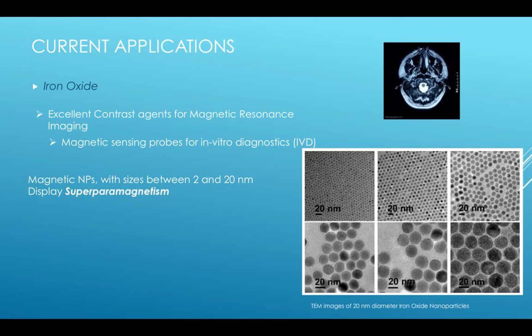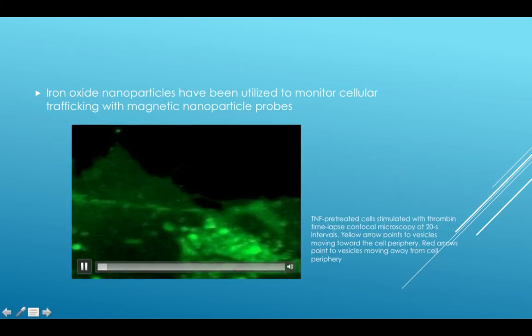Many metallic nanoparticles possess immense potential as X-ray and magnetic resonance contrast agents, and have a wide range of optical and medical diagnostic device applications. This is owing to their high attenuation, biocompatibility, and relatively low toxicity over a short period of interaction. MRI is based on the behavior, alignment, and interaction of protons in the presence of an applied magnetic field. Protons in the tissue are excited, and contrast agents are used to alter longitudinal or transverse relaxation times, which can be monitored by MRI to produce image data.